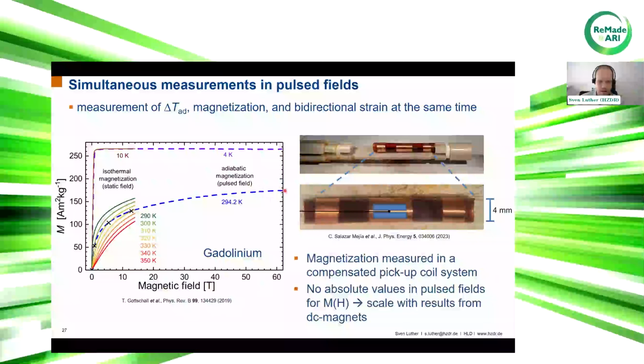because during the pulse we are heating up our sample, and at 60 Tesla we have a huge different temperature of our sample compared to the static field measurements. So you can see here, during the magnetization pulse, we are heating up and get a different magnetization curve.